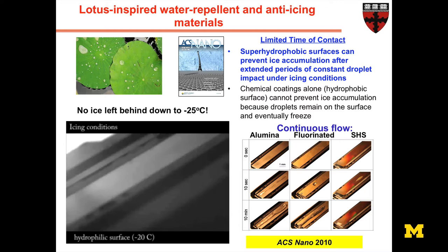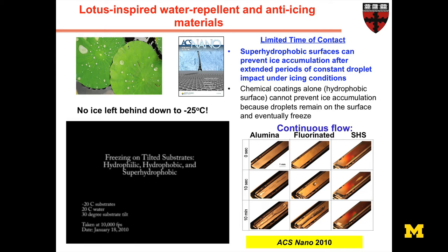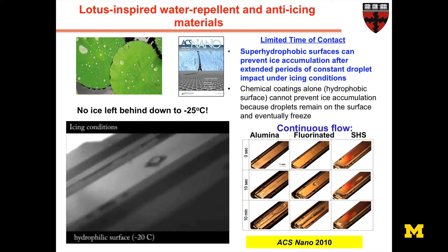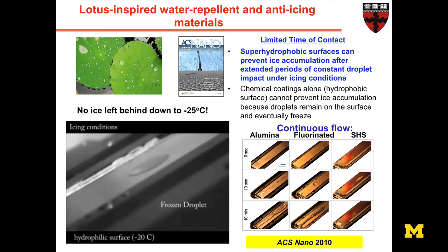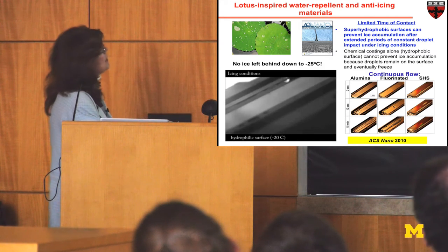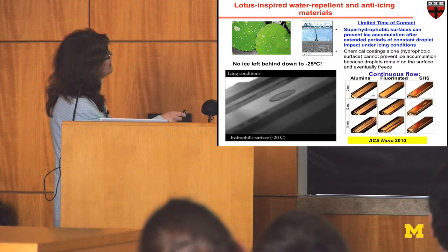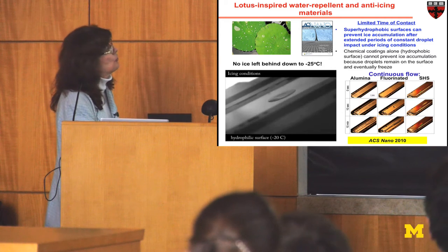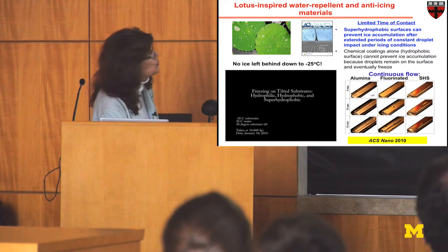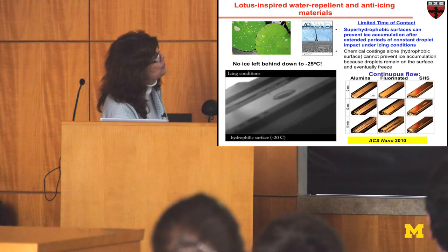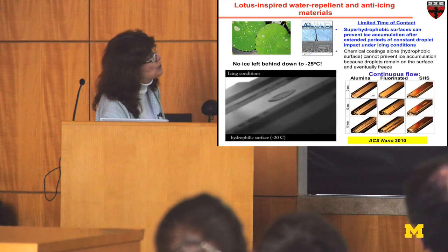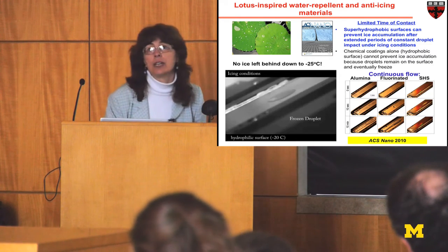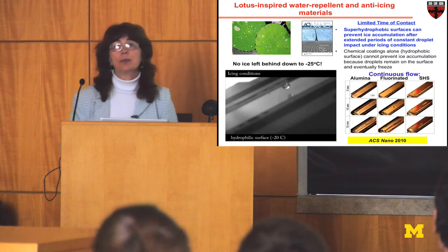And indeed, in fact, this is what we've seen. And this is a slowed down movie, hydrophilic surface. This is now minus 25 degrees C on the substrate, minus 5 degrees droplets. On the hydrophilic, they spread and immediately freeze. On hydrophobic, they spread the same way. They contract, but they're still in contact with the substrate, so they will freeze eventually. But on superhydrophobic surfaces, you can build it in such a way that the droplet is actually reflected from the surface before crystallization takes place, and in this way, it doesn't matter whether it's a single droplet or even continuous flow, you could see that these superhydrophobic surfaces stay ice-free in the continuous flow of supercooled droplets on supercooled